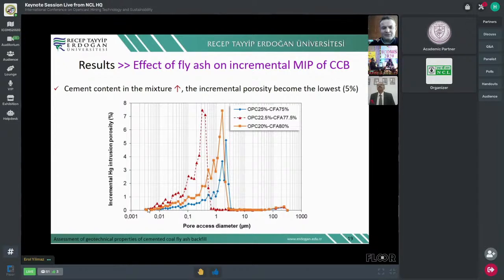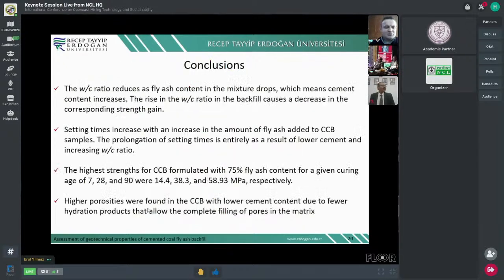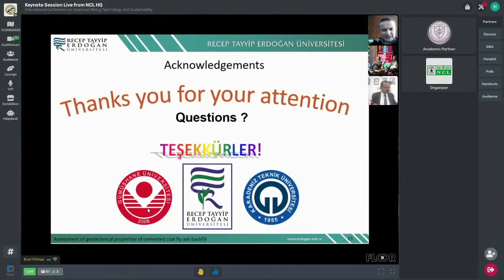And here also, as we can see, the water to cement ratio reduces as the fly ash content drops. Setting time increases with the increase of the amount of fly ash added to cemented backfill. Highest strength for backfill formulated with 75% fly ash content.